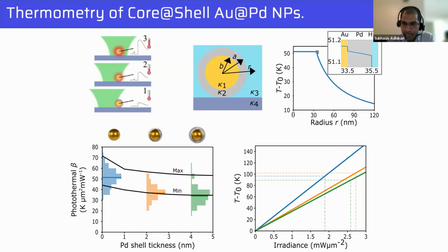I think we have a comment from Professor Croy. I think that's a comment, not a question, but I can also say it: with computer simulations of Lennard-Jones fluids, you get huge Kapitsa resistances because the fluid, if you heat it, becomes very dilute. The Lennard-Jones fluid is not like water, right? It's a bit more like a gas almost. So there you see huge Kapitsa resistances. But I think for instance, in a solvent like water, it is probably pretty hard to get such a strong effect, right? But maybe near the critical point, you could see such a thing.